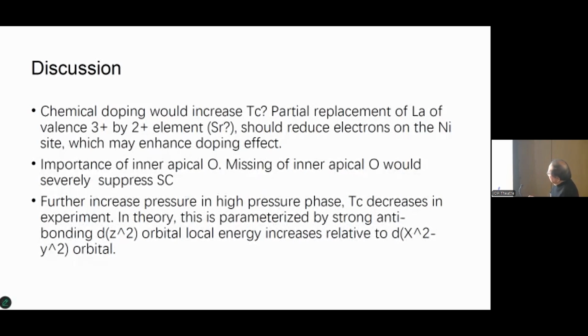And we also could address the pressure dependence. At lower pressure there is a structure phase transition, which is too complicated for us. So we may consider just within the high pressure phase, we further increase the pressure. Experimentally Tc actually decreases if we further increase it. And in the theory, this is just parameterized by the strong anti-bonding orbital local energy, relative to another orbital energy. And qualitatively, we may argue this would not favor the pairing.